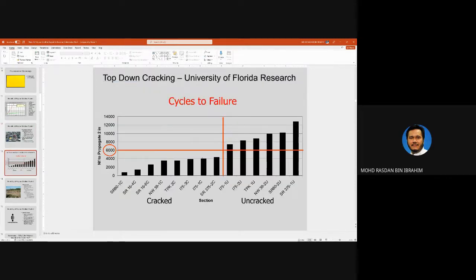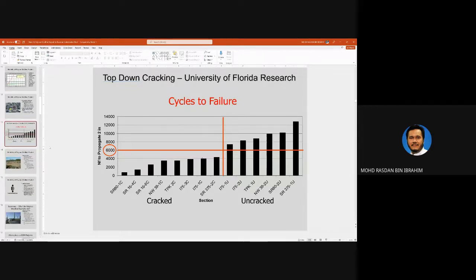So this is an example of cycle to failure research carried out by University of Florida. So this is a stretch of a test road. So between this and here, they have used different types of bitumen. So they measure the cycles to failure here. So very early in the cycle, this portion has started to crack. So the polymer modified one has better resistance. The problem is it is expensive, polymer modified bitumen.